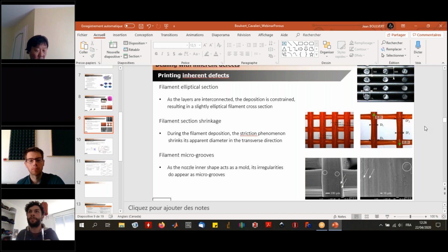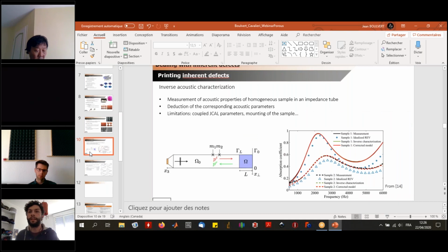And also one other point that you raised, Thomas, regarding the characterization. If I'm not mistaken, we do the retrieval of complex density and bulk modulus using 4 microphone techniques. And actually the impedance tube here uses 2 microphones. But what we do for the inverse characterization of the acoustic properties and transport parameters is use Bayesian techniques in order to fit the corrected JCAL parameters.